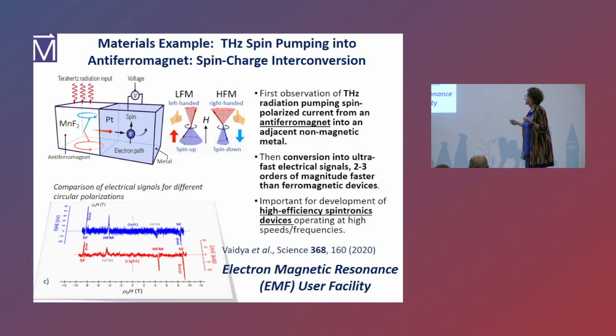Now, what happens is it's 2 to 3 orders of magnitude faster than your standard ferromagnetic devices that people study. And the reason for that is this coupling is due to exchange. It's not due to magnetic anisotropy. So that's been a fun thing to study.